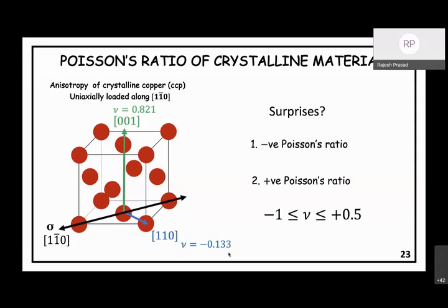A brainstorming thought is coming to me, whether because of the anisotropy, the bounds also will be anisotropic. That is, there can be some bound for loading along the 110 direction and a different bound for loading along the 001 direction. Yeah, it's possible, because generally Poisson's ratio for cubic is given as a combination of C11, C12, C44 probably. And you get conditions only on C11, C12, etc. And so using them, you should get what the bound is, I think.